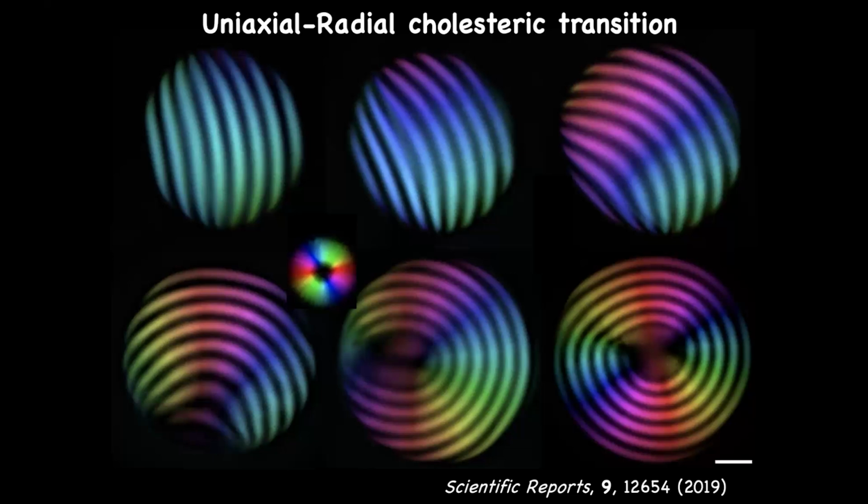The difference is now that you have a nematic defect in the middle, because this bending and the small radii of curvature are so high that it's just not sustainable. It would just melt into a nematic phase. So this is only one color here because this is melting into nematic. And if you work this out with scaling, you get back the same transition that you predicted before, because you pop in bending and you pop in the interfacial energy. Of course, there is an effect that can make it different, but this is not enough to stay.